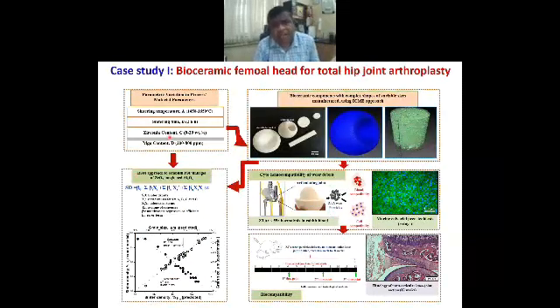This is one of the examples that we have done in zirconia and alumina, which is used for femoral heads, for example. Here we have used the response surface modeling approach. On the y-axis is the experimental sinter density, and the x-axis is the predicted sinter density. You can see that the predicted values closely follow the experiments, with an R-square value of 0.98, which is fairly good. This was possible using multivariate analysis in the response surface modeling approach.